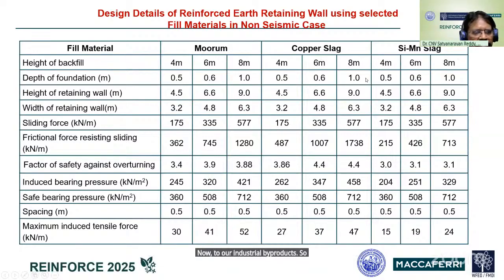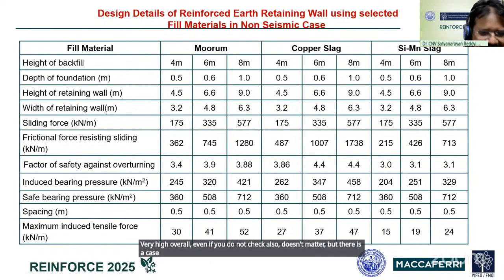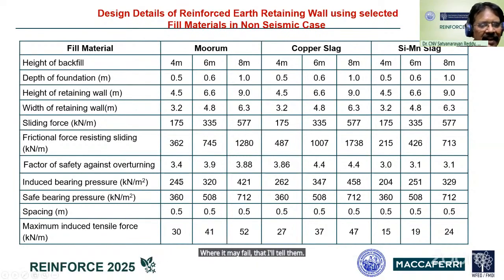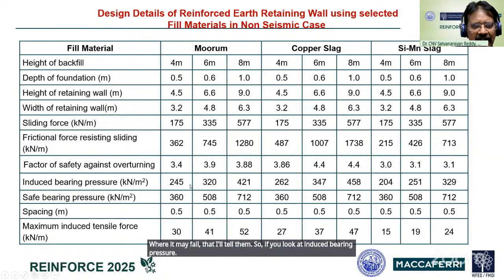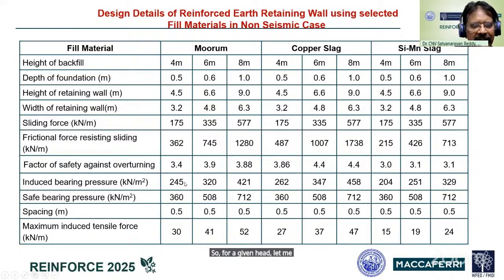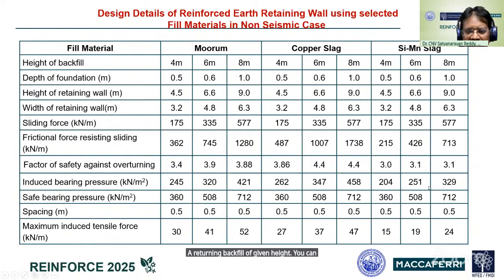You can see from these slides that the factor of safety against overturning is always very high. Even if you do not check it, it doesn't matter, but there is a case where it may fail, which I will tell. If you look at the induced bearing pressure, for a given height, let me say 4 meter, 245 kilonewton per meter square is the induced base pressure. Copper slag is inducing 262, whereas silico-manganese slag is inducing 204.